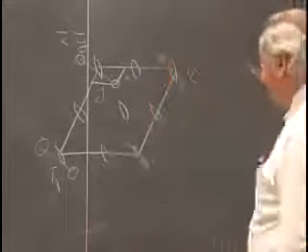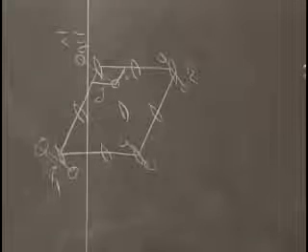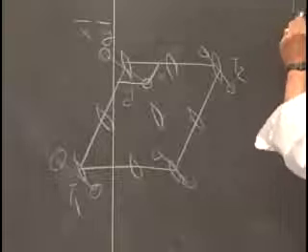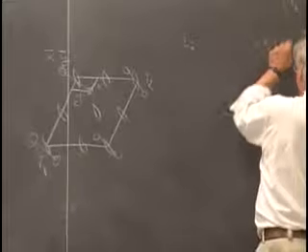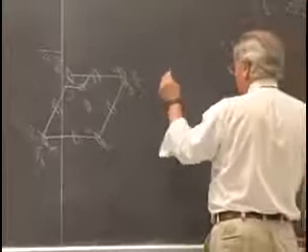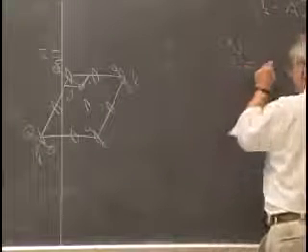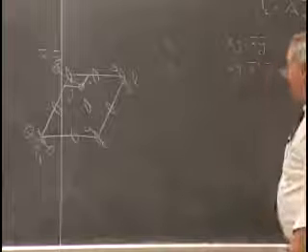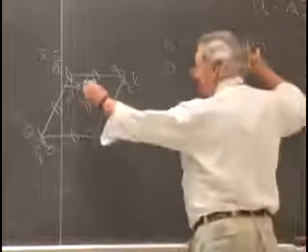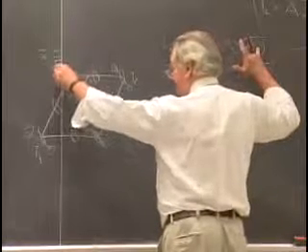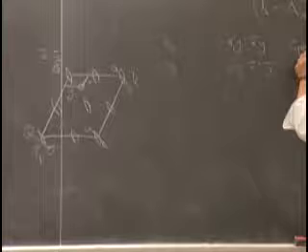So a characteristic of this plane group, if I were describing to you a crystal structure which had this symmetry, I might say something like a lithium in a position with coordinates x, y, and therefore minus x, minus y would also have to occur. I have an oxygen at a different position, x prime, y prime, and that must then also occur at minus x prime, minus y prime. And it looks as though anytime you throw in an atom at a location x, y, you get a symmetry-related companion to it with negative the coordinates. And this is what is called the general position of the space group.